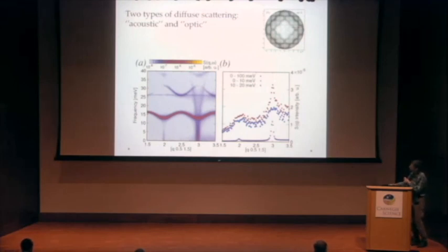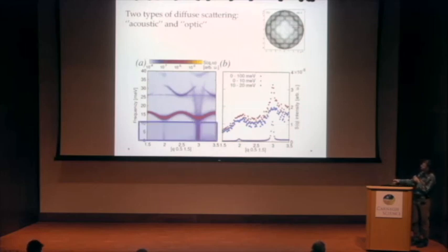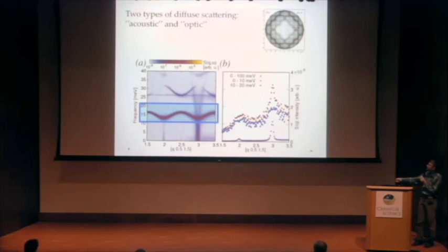We can do more. We can actually trace how to integrate the intensity part by part. For example, if you would integrate the intensity over the first 10 milli-electron volts only, then you would mostly get contributions from these pieces, and you see that it has peaks here and there, just in the position of the sharp lines. If, on the other hand, you would integrate between 10 and 20 milli-electron volts, you would integrate mostly this wave, this acoustic branch, actually the zone boundary, and this would give something which is much broader, and actually it's related to this intensity.